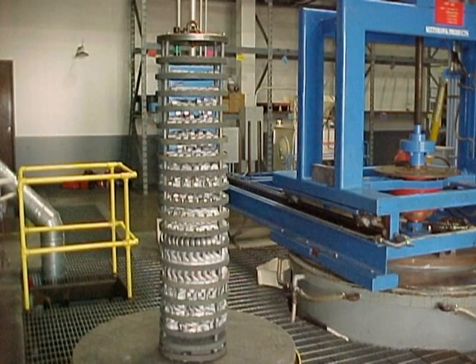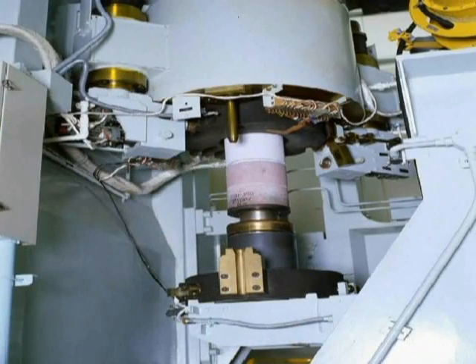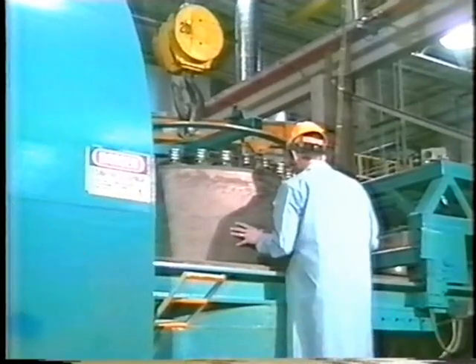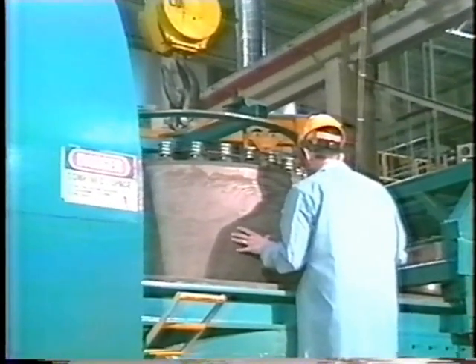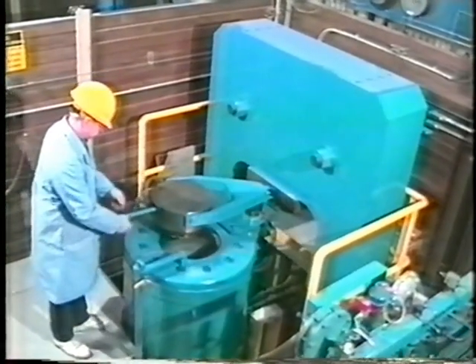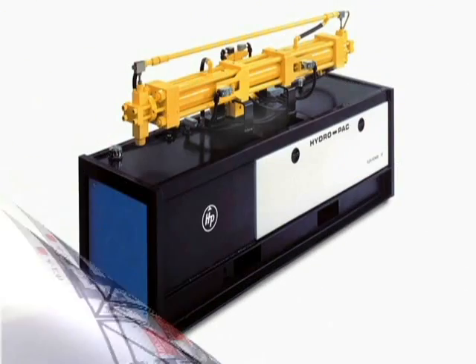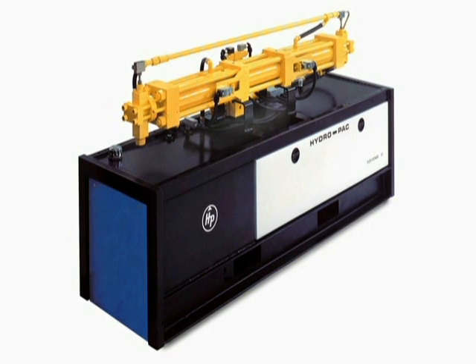Parts such as these castings are commonly loaded into some form of metal basket, which is then lowered into the furnace positioned in the pressure vessel. While this vessel loads from the top, some presses feature bottom-loading systems. An insulated thermal barrier surrounds the furnace to focus the heat load on the parts and away from the water-cooled vessel wall. The pressure medium is most commonly argon, which is fed from storage cylinders to an electrohydraulic intensifier that pressurizes the gas to the required level.